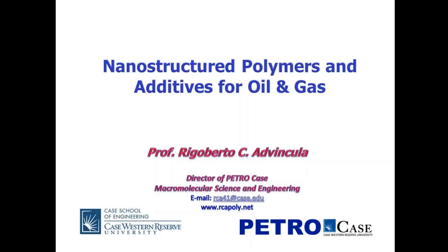Okay, so yes, the tools we use are as follows. We use X-ray diffraction to characterize periodicity. Of course, we also use imaging tools like SEM and TEM on properly contrasted clays. We use thermogravimetric analysis just to distinguish the organic and inorganic component. On the other hand, we are also interested in using different types of indentation tools, even non-indentation tools.